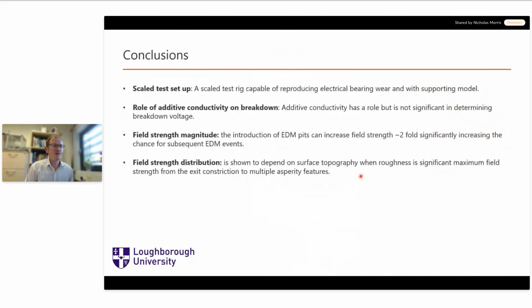So in conclusion, we've got a scaled test rig capable of reproducing electrical bearing wear and supporting model. And I'll show you some example data that we've used to investigate additive conductivity on electrical breakdown strength of the fluid film. And it shows that although it has a role to play, it's not significant in determining the breakdown voltage, and factors such as speed and load, which relate to EHL film thickness, are more important.